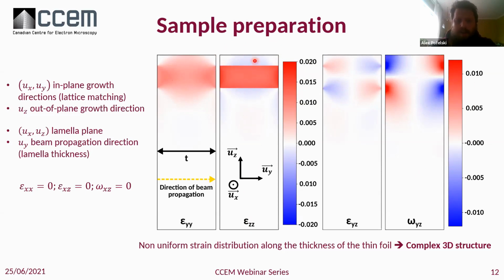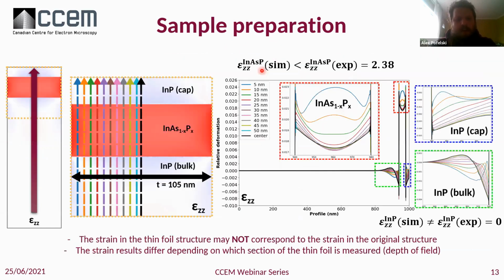uniaxial deformation. So if we take, for example, different line profiles at different locations in the thickness, this is the type of deformation profile we will see. We'll have a nice 0, then something positive in the layer, and some things going on just at the vicinity. And that's the very important part here.